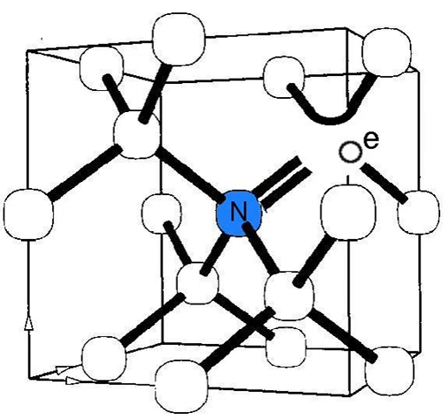Whereas many single molecular emitters bleach after emission of 10^6 to 10^8 photons, no bleaching is observed for the NV centers at room temperature. Because of these properties, the ideal technique to address the NV centers is confocal microscopy, both at room temperature and at low temperature. In particular, low-temperature operation is required to specifically address only the zero phonon line (ZPL).